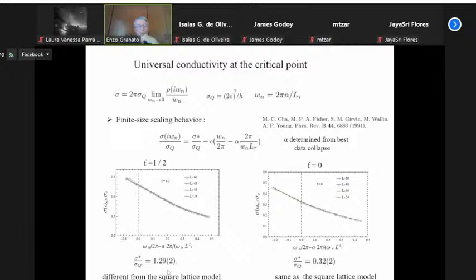for this model is 1.29, which is quite different from what we obtained for the square lattice. It's actually a factor of 4. So for frustration 1/2 in a honeycomb lattice it is very different from frustration 1/2 for a square lattice, and it's also different from the zero field case. So they are different universality classes. For the zero field case, the critical conductivity at the transition is the same as for the square lattice, but for the frustrated case, it's not, because it depends on the structure.